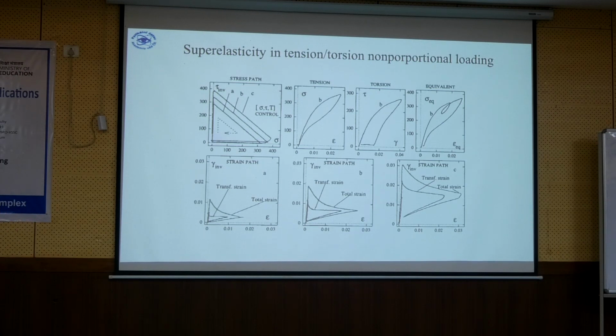In copper-based alloys, it's very difficult to introduce because the phase which is induced is typically this beta prime phase, and there is no reorientation in beta prime phase. So this beta prime phase, if you do such kind of exercise, the only way how it can respond means to go back, to have the reverse transformation. But in case of nitinol, the martensite under stress will change the orientation, will reorient. And this makes a very big difference.